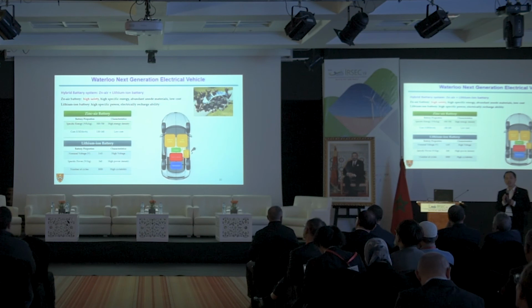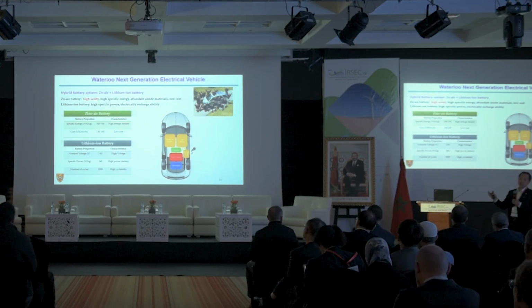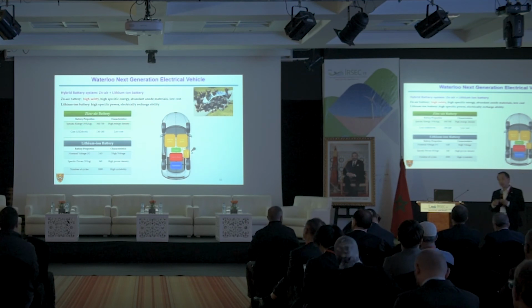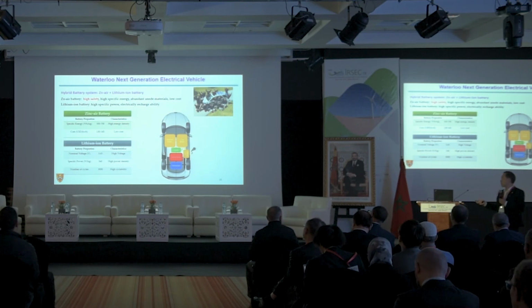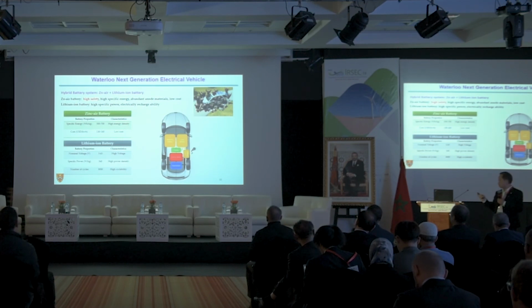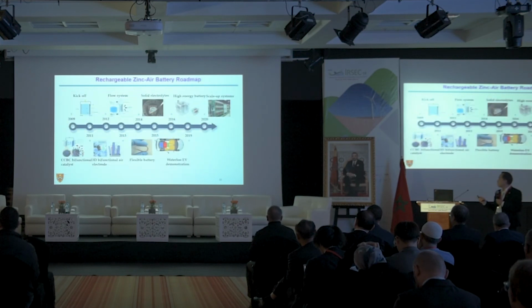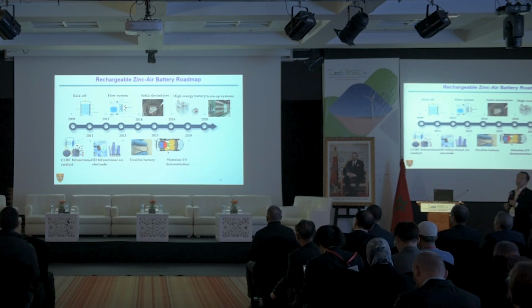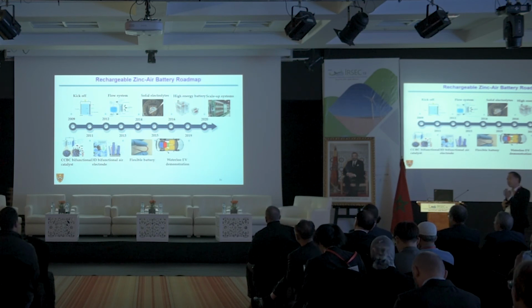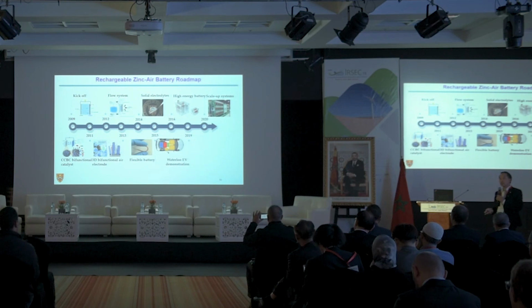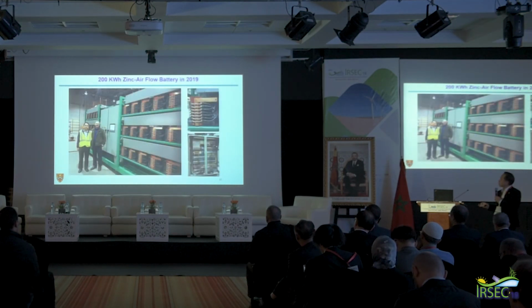Then in terms of that, the lifetime and cyclability requirement for the zinc battery doesn't need to be that high. Only several hundred cycles, and you can meet that requirement. So we did some calculation with modeling together with General Motors, and that's the idea we think could work in the future. So in the past 10 years, we did a lot of effort. We solved the catalyst problem. We solved the zinc dendrite problem, but definitely the zinc electrolyte still needs to be further improved. And now we're trying to go to demonstration. We did a demonstration this year.